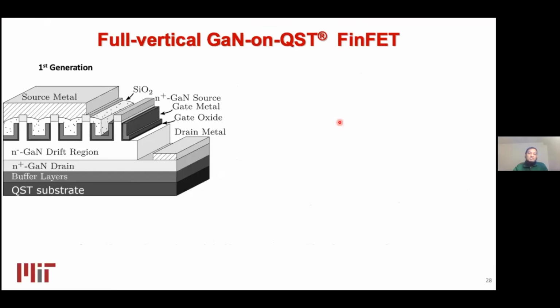So in the first generation of devices, we used a quasi-vertical architecture where our drain layer was not exactly at the bottom of the device. We still have the QST substrate remaining and the buffer layer used for growth. We etch down to the drain layer and put the source layer on top of this, so that we can probe from the top.